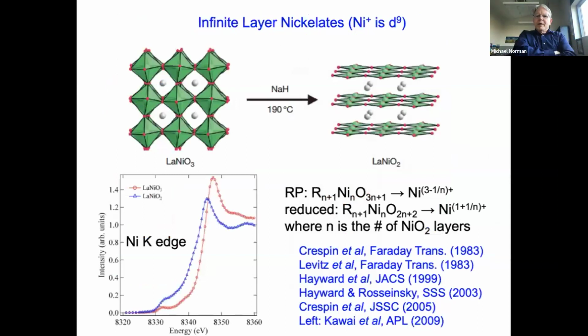So the infinite layer nickelate, believe it or not, which is obtained by topotactic reduction of the perovskite, actually predates the Bednorz-Müller discovery of high-Tc cuprates. The work goes back to 1983 from several groups, including Mike Hayward's group. What happens here is you start out with a valence of 3 minus 1/n, where n is the number of nickel oxygen layers. And by stripping out the apical oxygens, you go to 1 plus 1/n for the nickel valence.